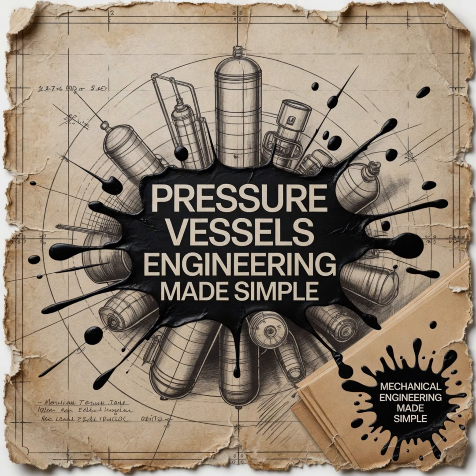So how does UT work? You've hit on the exact reason why modern codes increasingly favor UT. Ultrasonic testing uses a transducer to fire high-frequency sound waves, often at a shear angle, deep into the steel. Sound waves. Yeah, sound travels perfectly through solid, homogeneous metal, but the moment the sound wave hits a planar defect, an acoustic boundary like a lack of fusion crack or a delamination, the sound wave bounces back. Like sonar. Like sonar. The technician watches an A-scope screen, and they see a massive spike in the echo return. UT is incredibly sensitive to those deadly, planar, crack-like defects that RT might miss.